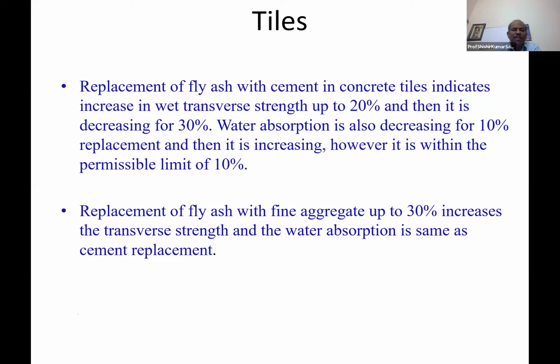Tiles: replacement of cement with fly ash in concrete tiles increases the transverse strength up to 20% and then decreases at 30%. Water absorption also decreases and then increases. However, it is within the permissible limit of 10%. Replacement of fine aggregate with fly ash up to 30% increases the transverse strength, and water absorption is the same for cement replacement.